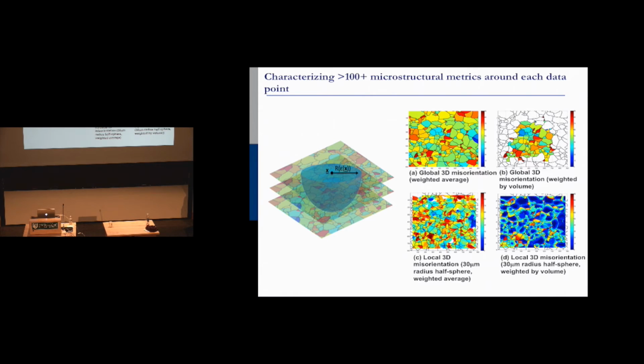For example, you can look at how misoriented you are on average. You take all the grains around your grain, and you say, 40% of my boundary is misoriented by this, 60% of my boundary is misoriented by this, this is my number. You can do it by volume. So instead of saying 40% of my area and 60% of my area, you can say that the 40% that's really misoriented has a huge grain, so it's going to be a little bit harder to move, so I should count it more. And you can imagine looking at the local misorientation in a half sphere too. So there are hundreds of these maps that we build that tell us characteristics: what's your grain size, how close are you to a grain boundary, different distance metrics to think about microstructure.